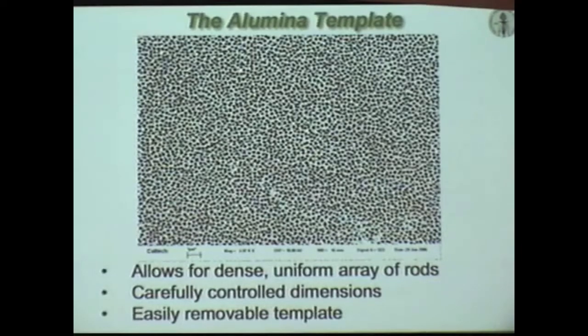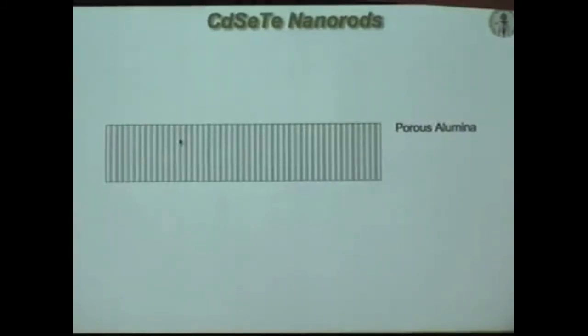You can electrochemically control the pore diameter by etching current density, as well as the pore depth by how long you etch. We can do this over large areas. This is a 1 micron scale bar, and it gives you a feeling for what we can do with this template. We can then electrodeposit in those pores a material. This is a test material in this case, cadmium selenide telluride.